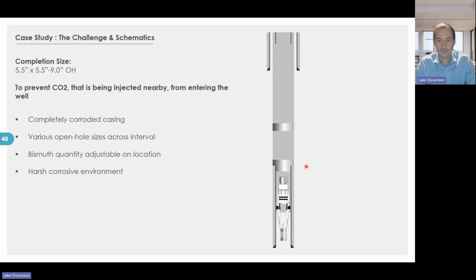There was a CO2 flood enhanced oil recovery well located about a quarter of a mile away, that over time, that CO2 flood had actually come in and compromised the 5.5-inch casing that used to be part of this wellbore envelope. And they had pressure at surface inside and in the annulus of that 5.5. So they wanted to try to remediate that problem with BiSN.